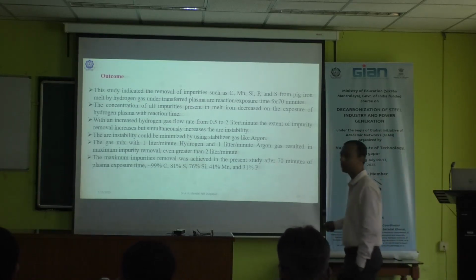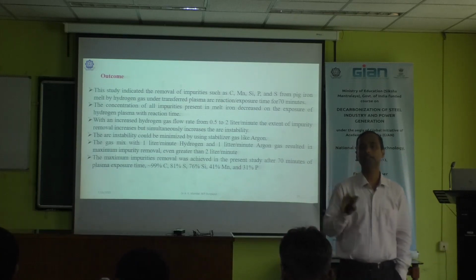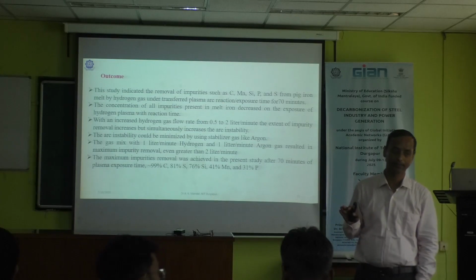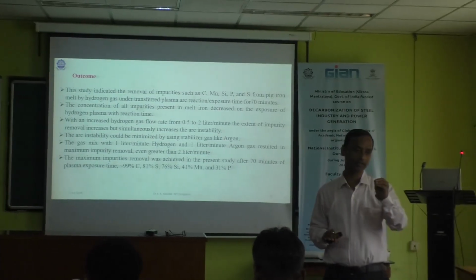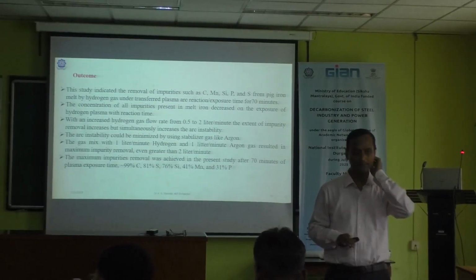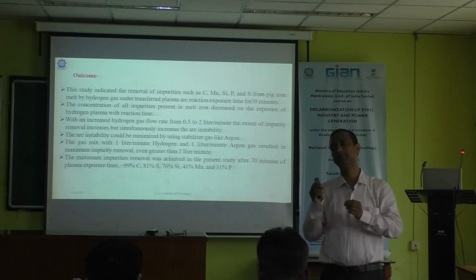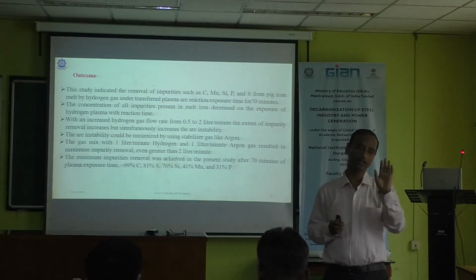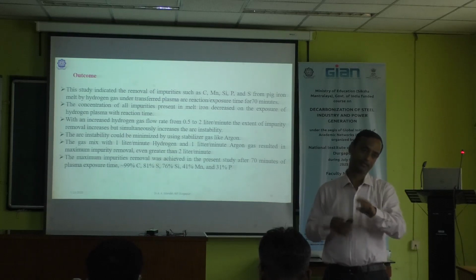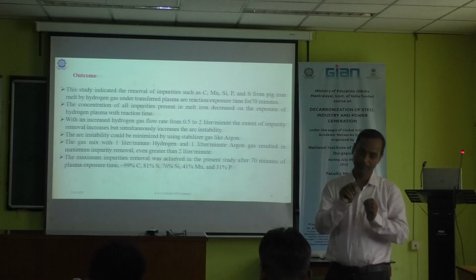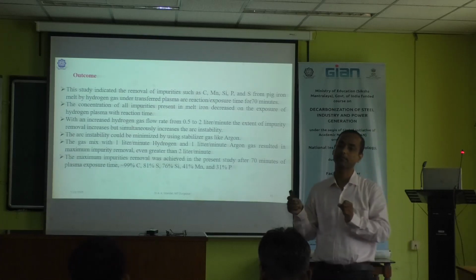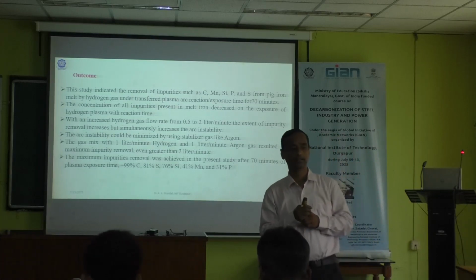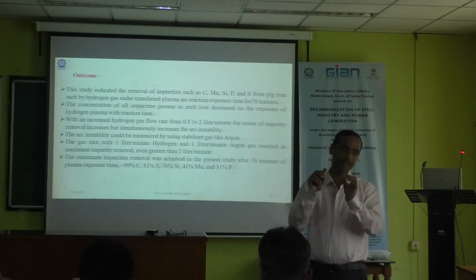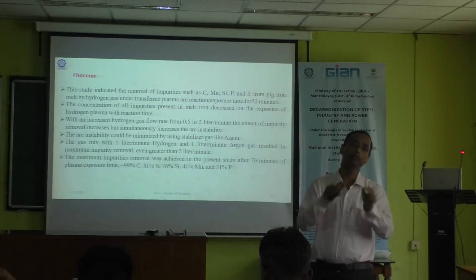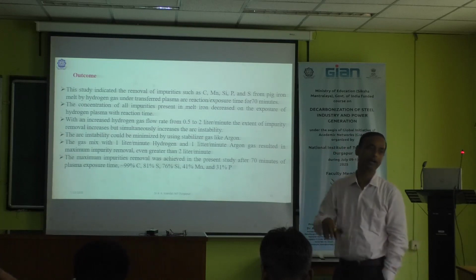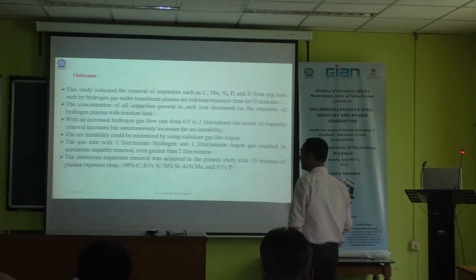So it means we have achieved the steel grade, normal carbon steel grade. Initially one system was pig iron, and for different systems I have to do this. When we prepared the Fe-C-S system, we took only pure pig iron and mixed in sulfur to make the iron-sulfur system. After that, the Fe-Mn-S system: from the Fe-S system, we added the manganese. In another system, we added the phosphorus. In this way we prepared the mix first. After that, we passed the hydrogen gas.